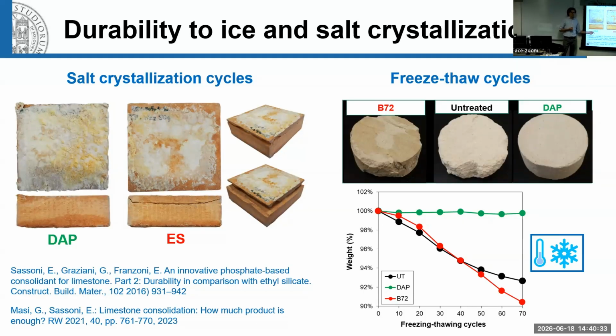By using this alternative treatment that we propose based on phosphates, we have formation of salts on the surface, which is not beautiful, but at least we are not damaging the monument, because in this case, the stone remains hydrophilic all the time, so we don't have this kind of problem. Also, in the case of freeze and thaw cycles, you see there that in the end, the final result is that we obtain better results compared to alternative commercial treatments.